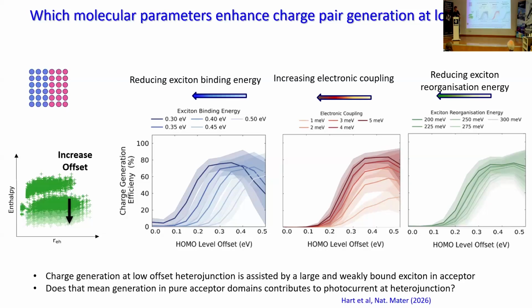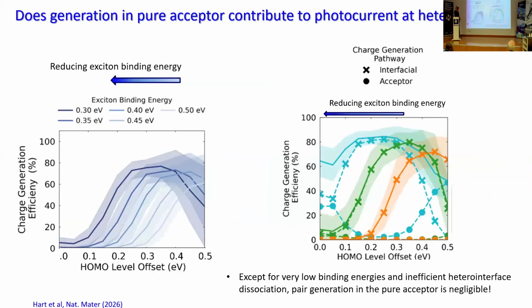This then raises a question. So this can help us to understand why with this new family of acceptors, we're able to get a good photocurrent quantum efficiency at a relatively small cost in terms of this offset. But it also allows us to ask a different question, which is, could it be possible that these solar cells made with the new acceptors are working very well because you can generate charge pairs directly in the acceptor material? I raise that question because it's been raised a lot in the literature, and this tool allowed us to look at it and find out, could that be the case? And basically we concluded no, and I'll try to explain why here.